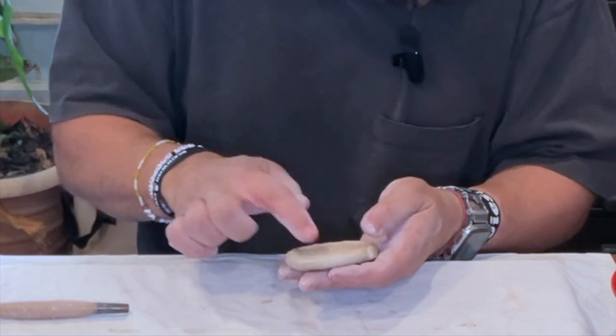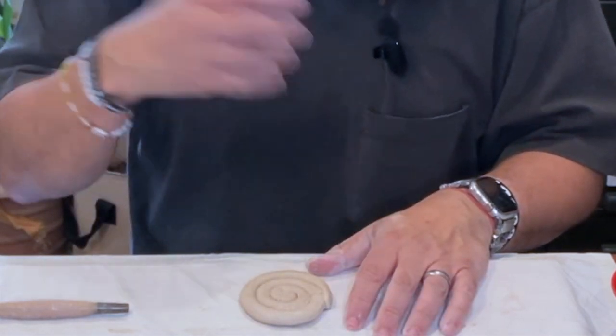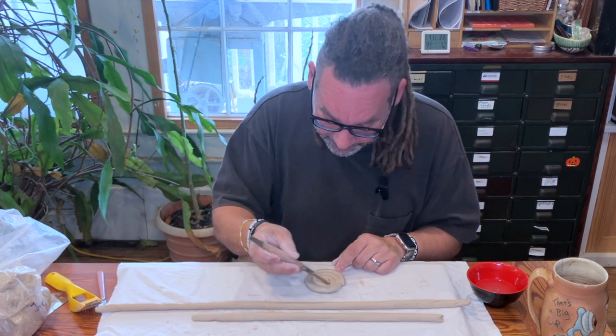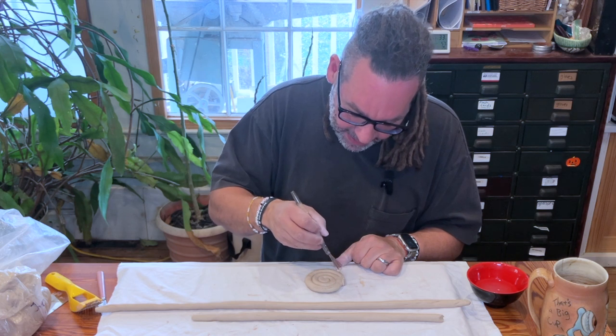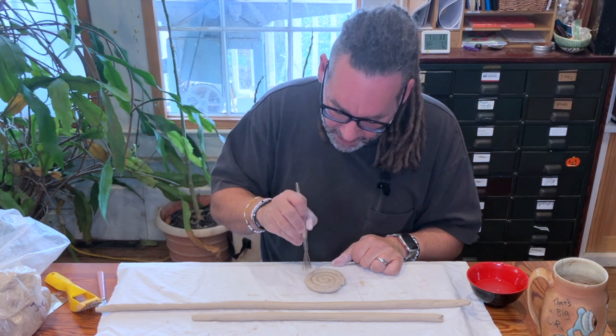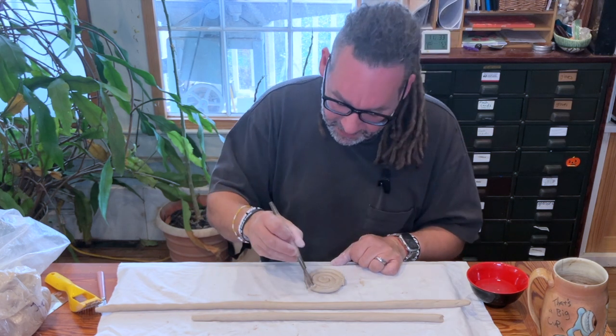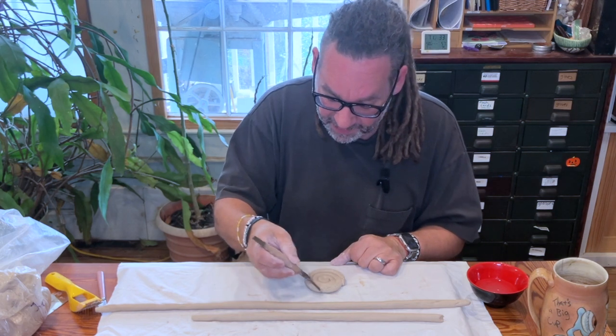We're taking something which is a semi-solid, and we want it to be drying in the most efficient way possible. So constantly adding water back into the mix is going to slow that down for us. And clay is going to shrink. This one's going to shrink about 11% from wet to finely fired. And the more I keep changing different parts of it as far as their moisture content, the more issues I might run into with bits of it shrinking